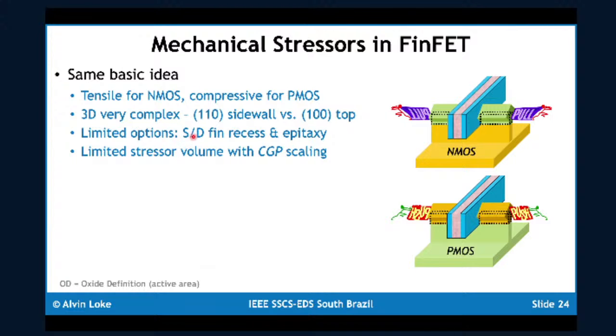And because we're continuing to aggressively scale down the gate pitch, it's making it more and more difficult to incorporate stressors, because you have less volume of stressors to squeeze or expand the channel in between. With all that said, the result is that these techniques are much more effective for PMOS than for NMOS, meaning that the beta ratios, or relative strengths of NMOS relative to PMOS, have been approaching unity.